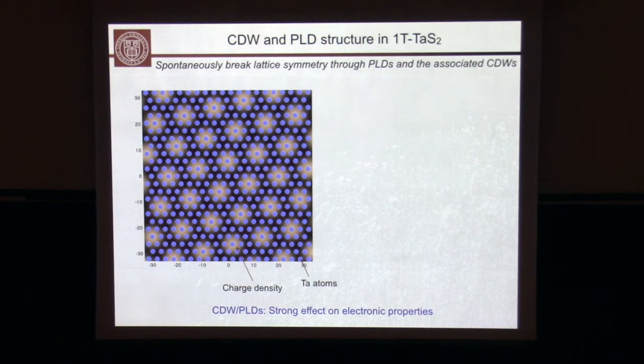So this is 1T tantalum disulfide. It's an exfoliable material. Some of you might work with this. The blue atoms are tantalum atoms. And now I want you to imagine that we have a charge density that is distributed where orange corresponds to maximum in the charge density. So if you have this charge distribution, you might imagine that atoms can respond to this charge. And in this particular case, they do. Here's a simulation of how you would imagine this happening. And you see atoms moving towards the center.